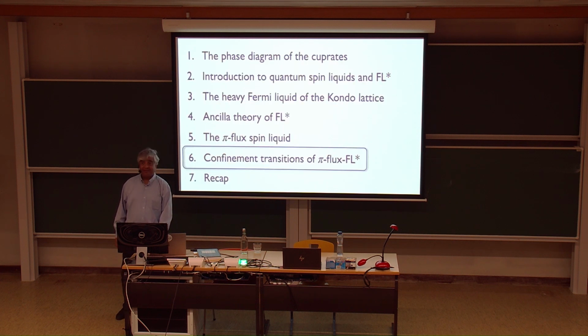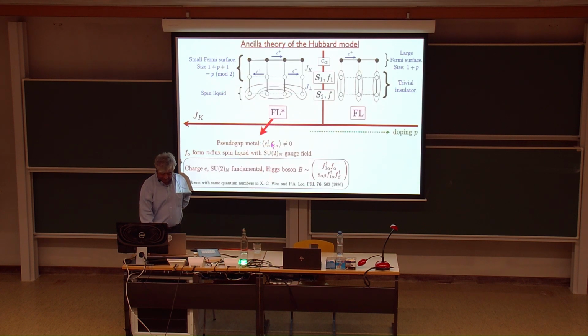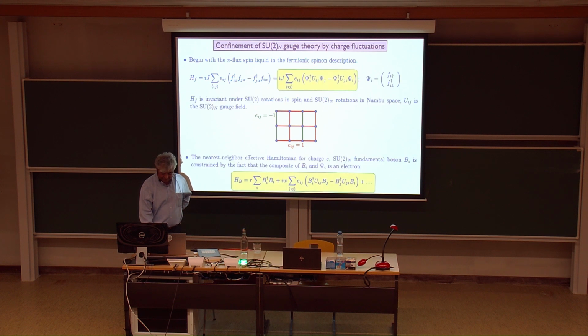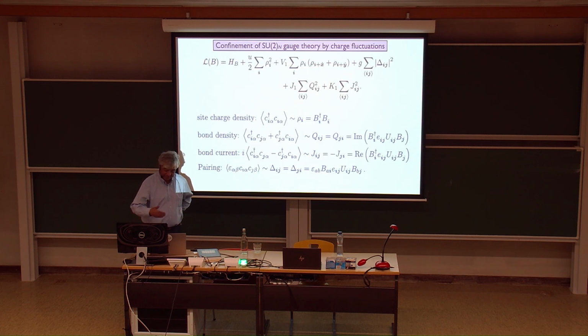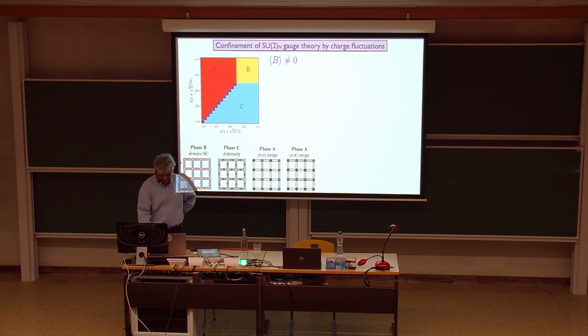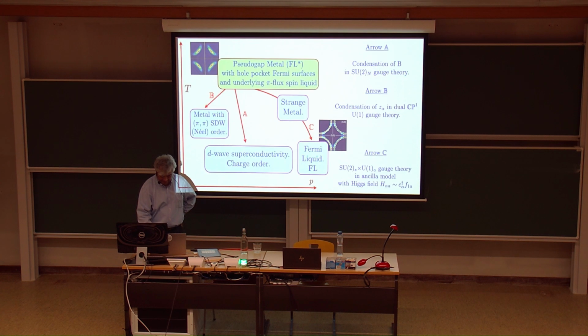All right, so finally, I think I'm out of time, but now we have to put all this together. I have a theory of the pi-flux spin liquid, and then I have to now confine it at finite doping in the FL star state. And well, anyway, how do I do it? You start with the pi-flux, then you put in some charged boson, which you argue must also have pi-flux. Then you look at the instabilities of these bosons. These are Higgs fields, so there's a fundamental Higgs field. It has various flavors, and in fact, its condensates have exactly the right type of order. It has stripe order. It has D-wave superconductivity, and you get some beautiful phase diagram that we're still working on.